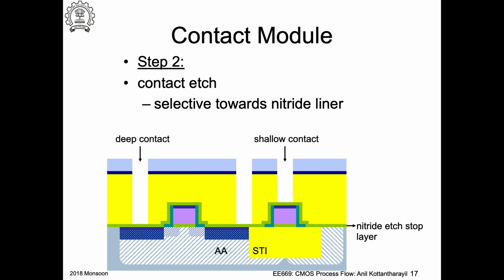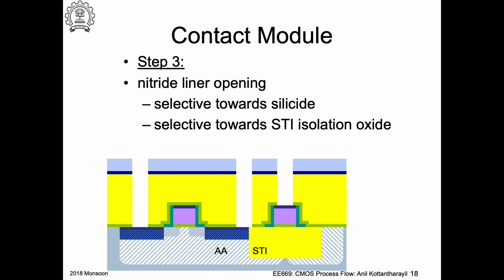Okay. Of course, you want to make the contact, right? You're going to put metal to contact your source drain and the polysilicon gate. Okay. So if you have the silicon nitride there, I can't do the contact, right? So I need to etch the nitride liner. Okay. So this should be selective to silicide, but then one good thing here is that I'm going to etch the nitride of same thickness from everywhere. Okay. So I'm going to etch this. I remove the nitride. Now I have this silicide from the top of the polysilicon and the source drain exposed.